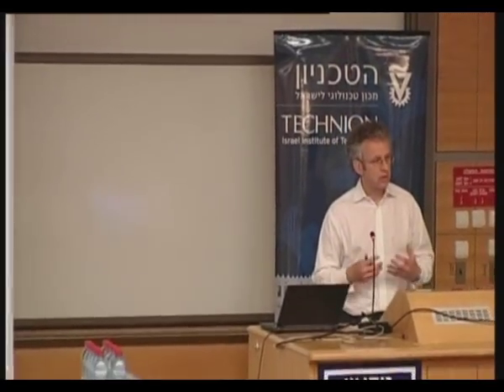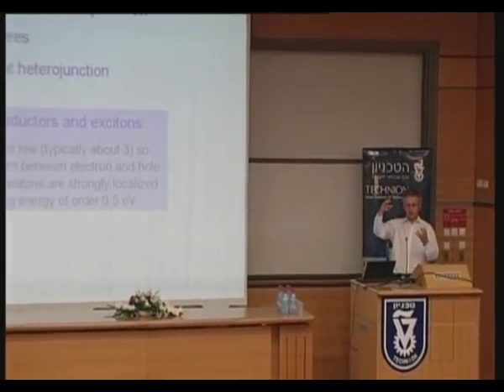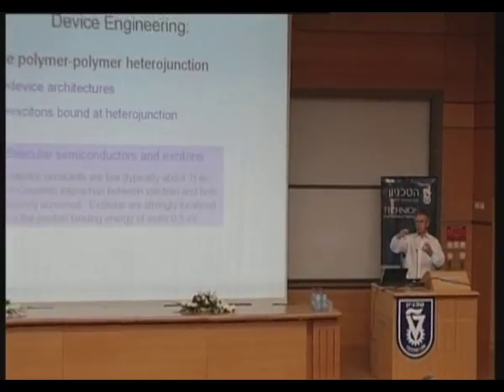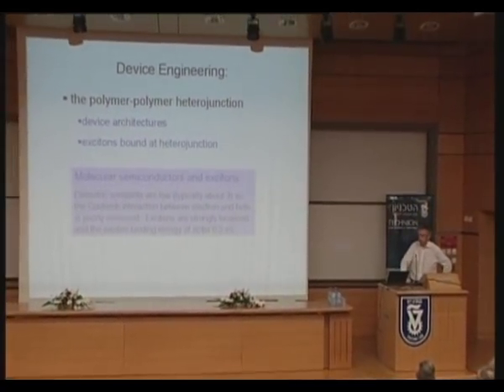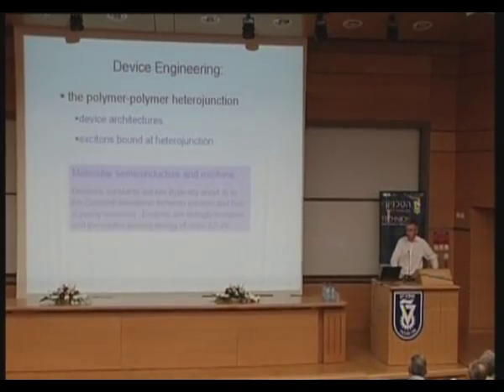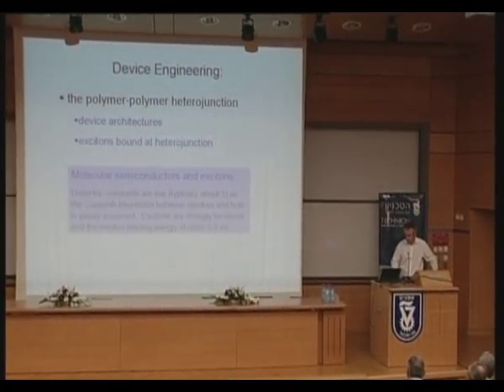And if I wanted to characterize quite generally how molecular semiconductors are different to inorganic semiconductors like silicon, it is in the strength of the Coulomb attraction binding between plus and minus charges. Molecular materials in general have relatively low dielectric constants. They will, say, have refractive indices of less than 2. And what that means is that there's very little screening between plus and minus, so that an excitation consisting of a plus and minus charge will remain coulombically bound by about 100 times more strongly than in gallium arsenide or silicon. So we have a binding energy of perhaps half an electron volt for an exciton.